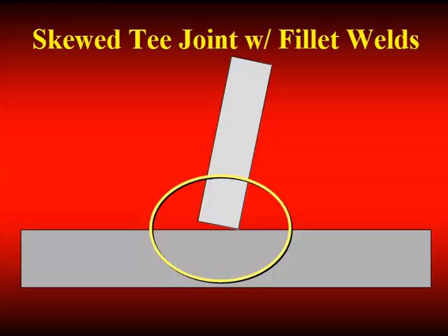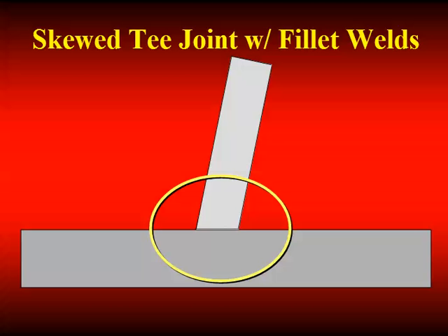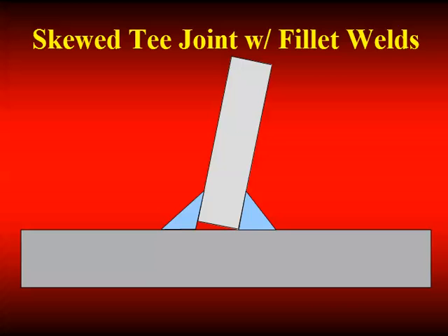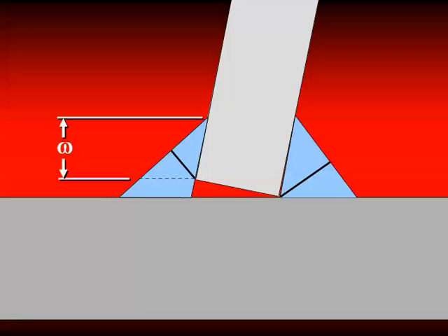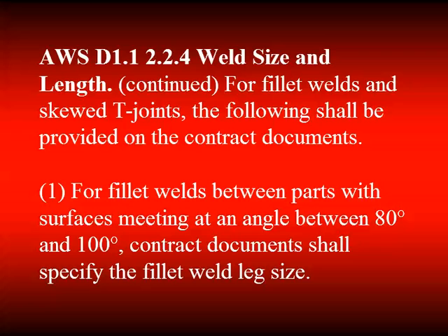It's going to be more costly. It's not the routine practice, but that surface could be cut with an angle, a bevel angle, that's the same as a skew, so when the two are brought in contact, there's no gap between the two. Now, the weld detailing that's applied makes a difference depending on that root condition. And if you have a gap on one side, notice that the weld throat is not going to be represented by what you look at of the external fillet weld, but you need to subtract from the leg size the amount of that gap, because your throat dimension is going to be the least dimension from the face of the weld to where that root starts. And if on a job somebody's measuring this total dimension and thinking that's the throat, you're getting a smaller weld than you think.